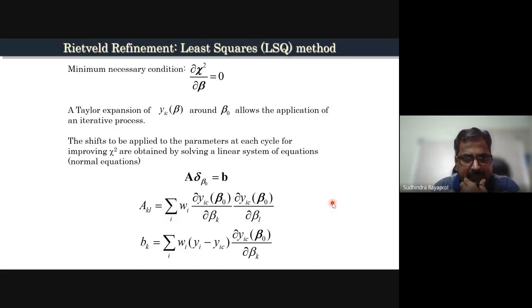What we are basically doing is that the least square method, or the Rietveld refinement method, is an iterative method. So we are refining a certain set of quantities, and we have given certain boundary values, so that if the difference between two successive cycles is beyond a minimum necessary condition, then it will go to the next cycle. Otherwise, it will converge. Since it is a statistical program, the idea is to minimize the difference so that the refinement cycle can converge at a certain point. The value at which it converges is the minimum of that particular quantity. Okay, so we are refining, say, 5 quantities. Once it has reached the minimum of its value, it will converge. Otherwise, it will go through repetitive cycles till the number of cycles we have specified.